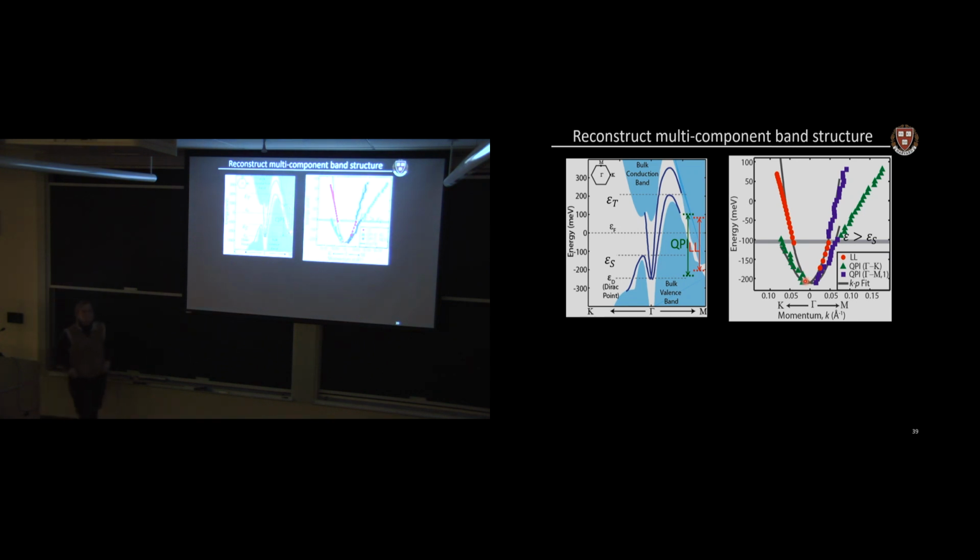Yeah? So do you pepper these defects on the surface, or do you have to worry about things that are buried in the bulk as well? So this is a semi-metal, which means that the things that are in the bulk are pretty well screened from the surface. The screening length is relatively short in this material, which is actually why it's really good for testing out these techniques. But if we have tried to study materials accidentally that are too clean, then we don't get this scattering at all. So very occasionally, we find that we have to intentionally put dirt into a material, but usually the reality is whatever we grow, it has enough dirt that we can do the technique without trying. Sometimes it has so much dirt that we can't see anything, it's all incoherent. This time we were lucky, it had just the right amount of dirt.